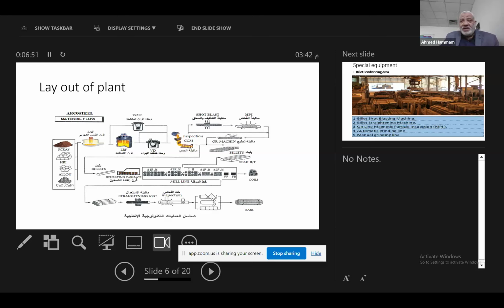After that, in the electric arc furnace, normally you get rid of the phosphorus and sulfur, and after that, you put the steel in the ladle furnace. In the ladle furnace, we can control the chemical additions for the different alloys in order to reach the desired final chemical composition. After the ladle furnace, we go to the vacuum degassing. After the vacuum degassing, the billet is coming to the CCM machines, which is also an item to be considered for the casting. It's a closed casting for the special steel.